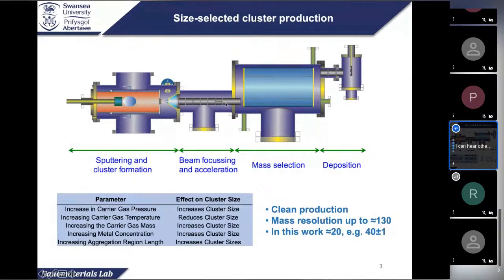When the cluster beam goes into the mass filter, you generate a pulse, giving the cluster beam a vertical momentum. Then the particle goes up to this section, and you give it another momentum, opposite to the one you just gave. You slow down the nanoparticle vertically, but it doesn't change the horizontal momentum. Then the cluster with the specific size will pass through the mass filter and go into the fourth section, which is the deposition chamber. With this cluster source, you can create nanoparticles below 10 nanometer. You can generate a single atom cluster beam.